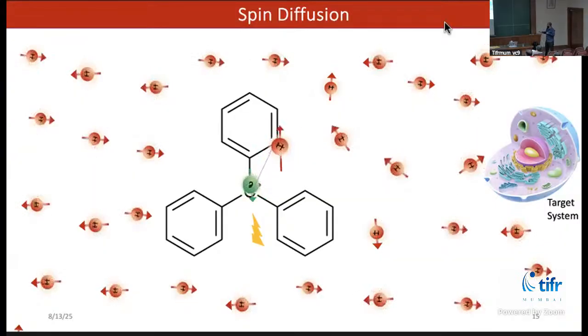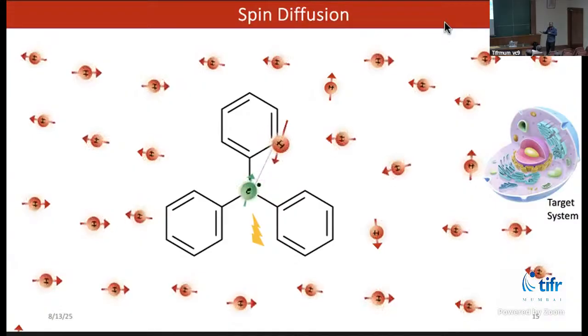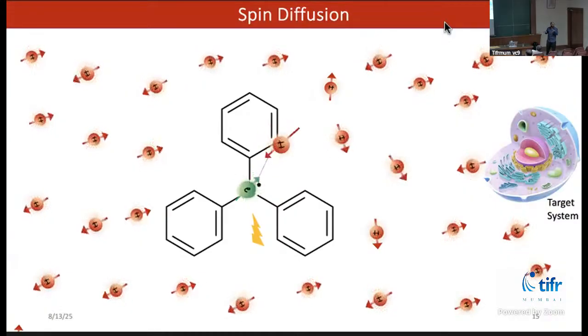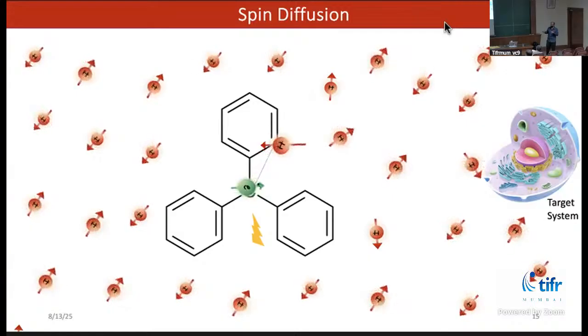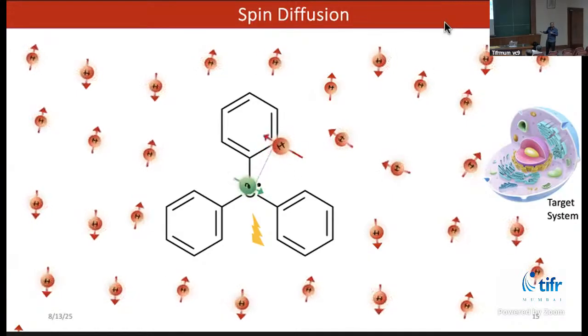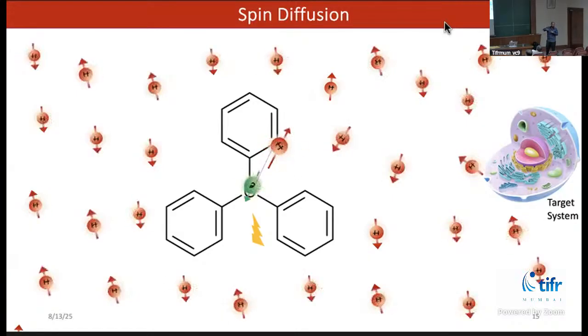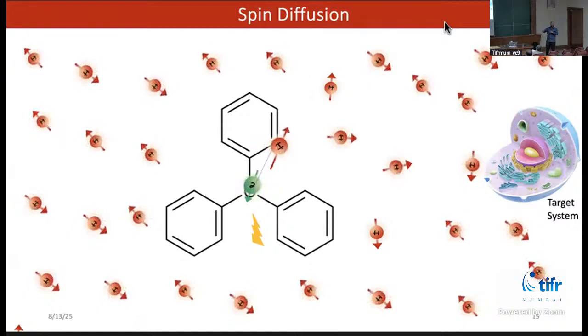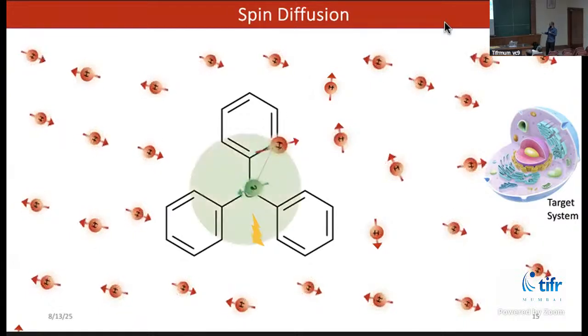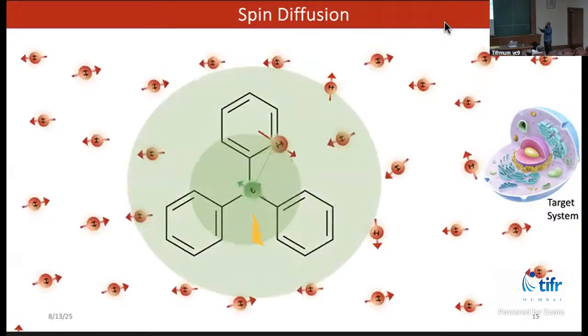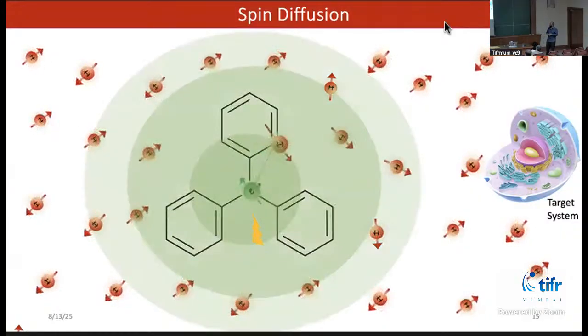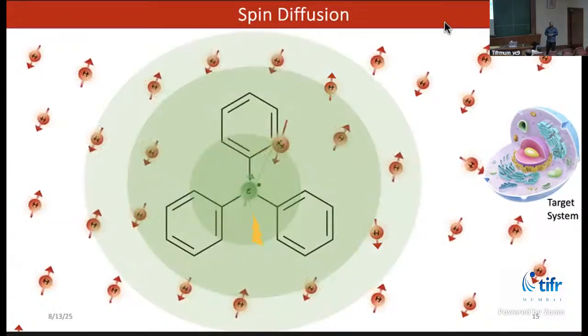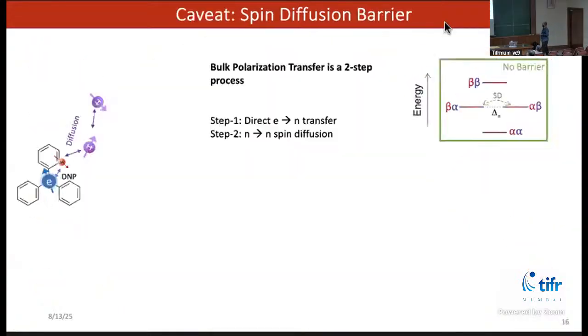So even if the target molecule is not close to the radical, we don't have to implant the radical on the surface. Even if it is far apart, because of spin diffusion process, the polarization can spread from the radical to the target analyte. So one can think of polarization as spreading like an onion shell. So this is what happens, but there is one caveat here in this spin diffusion process.